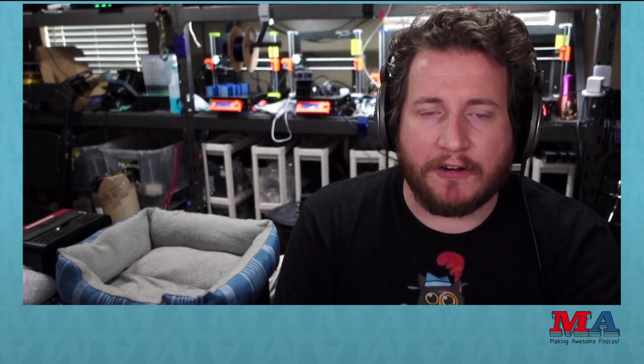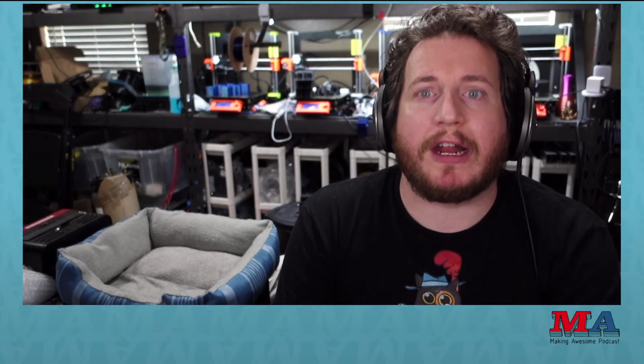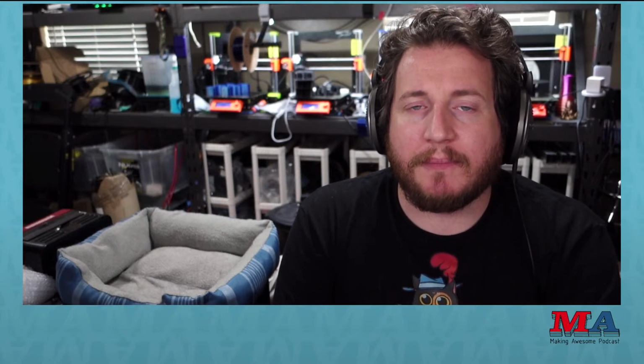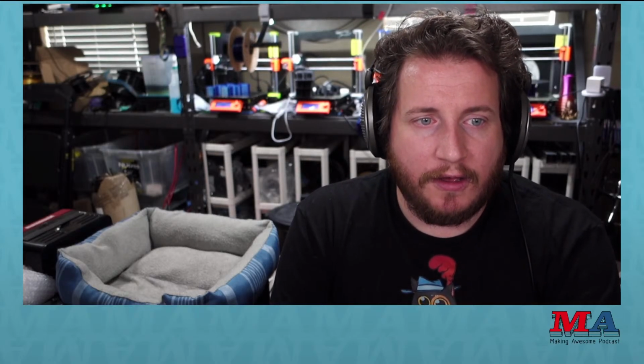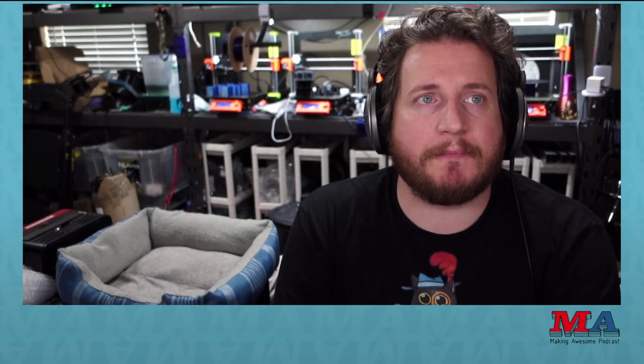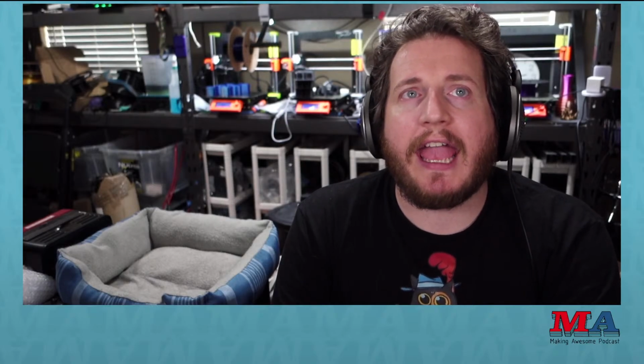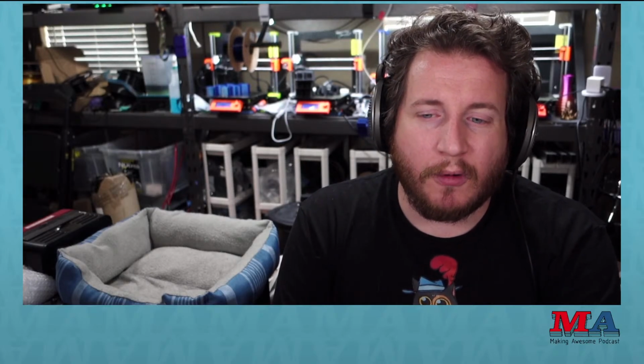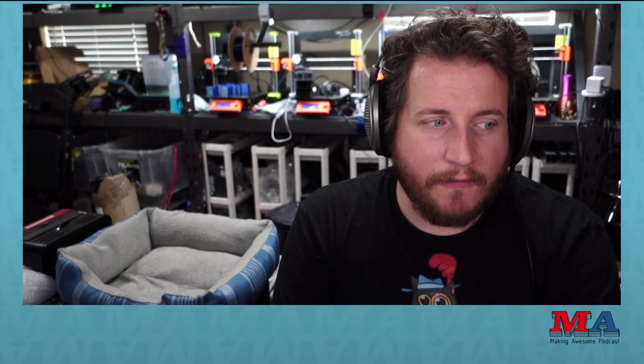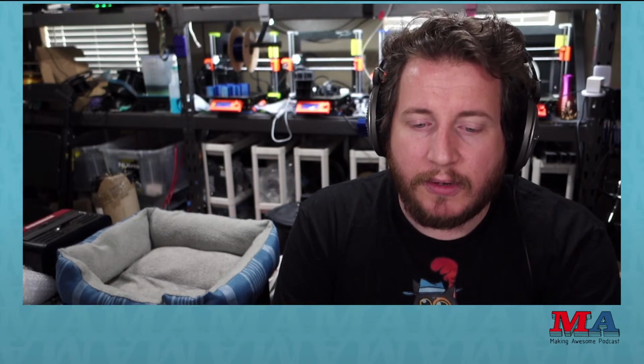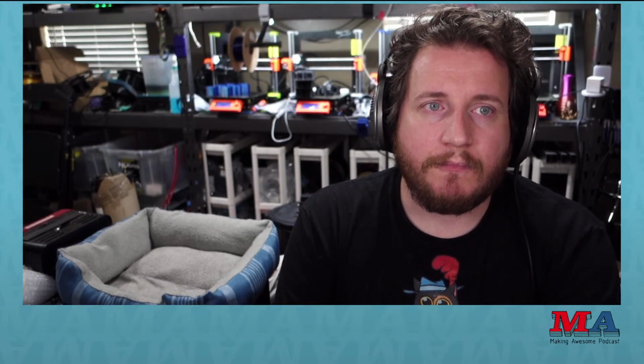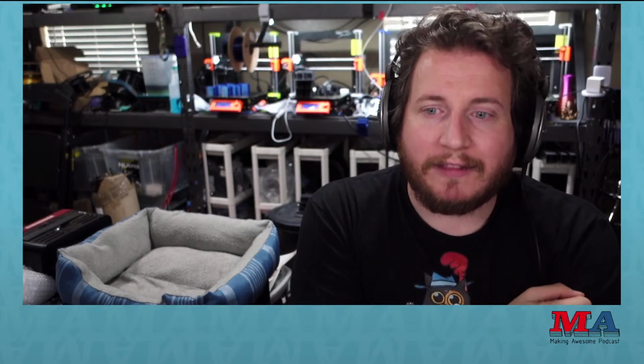Nylon has the unfortunate problem of being incredibly hygroscopic. It absorbs water faster than it just... God, we can't have nylon in open air for more than about 2 hours here before it pretty much becomes unprintable. There's very little that we can do to stop that. And so often we print directly out of dry boxes.